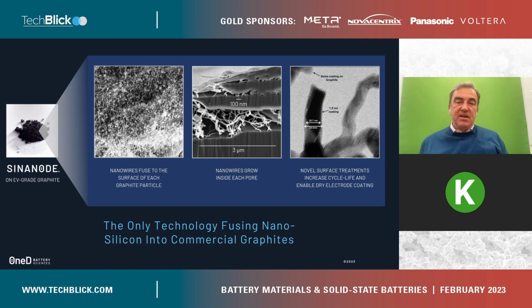And the picture in the middle of the screen is basically showing you a cut of a graphite particle. This one is a commercial graphite powder from Nouveau Monde in Canada, but we have done that with others. And if you cut the particles, what you see is that there are those big pores inside the graphite particles. I must say that we start with uncoated natural graphite. And so the little white hair that you see in the middle of the slides are basically like little extension cords. They are made of silicon, and they are plugged into the graphite surface like an extension cord would be plugged into the plug of a wall.